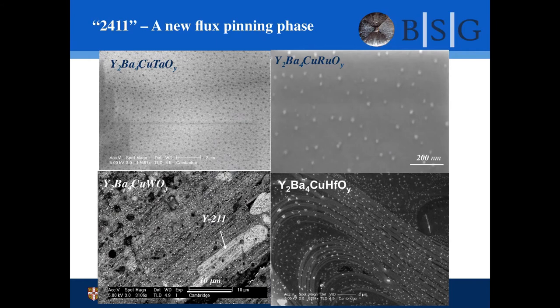We've also developed a new flux pinning phase. We call it the 2411 phase. So in this case, it's yttrium, barium, 4, copper, 1, tantalum. And you can replace the tantalum with almost anything. And if you get this right, you get this very fine distribution of second phase materials.